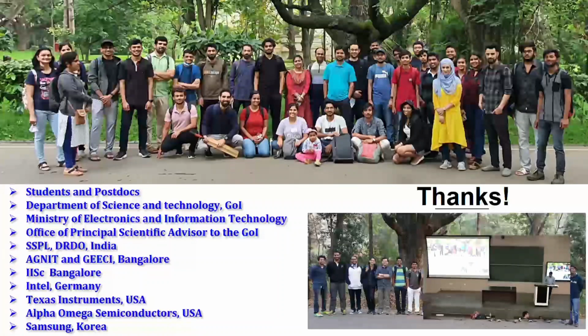So computations, a lot of things can be shown, but then you need to have a process. How do you do that? Even for example, I had shown you that suppose you introduce these sulfur interstitials, right? But if we had not discovered that method to bring those sulfur interstitials, the findings from computations are of no use. On top of that, you need to build something which is scalable, right? So it has to be scalable, it has to be experimentally possible, and it should be repeatable. That 1T phase conversion is something which people have talked about. Even there are other techniques, but either they are not repeatable or they are not scalable.